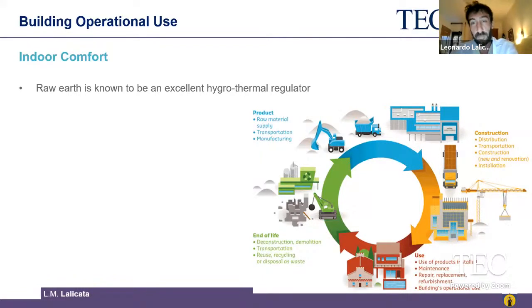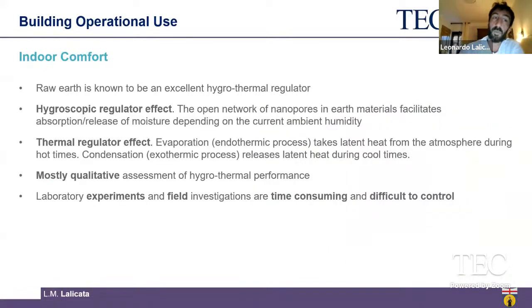hygro-thermal regulator. And here we need a bit of definition, I'm sorry. So with hygroscopic regulator effect, which means that the wall is capable to absorb and release moisture depending on the current ambient humidity. And this is possible because of the open network of nanopores that are present in the earth materials. As a consequence of this, there is also a thermal regulator effect because the evaporation and condensation processes that occur during this absorption and release of moisture need energy. So during evaporation, the soil tends to absorb the heat from the atmosphere that is released during the condensation phases.